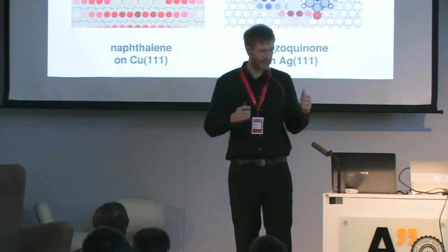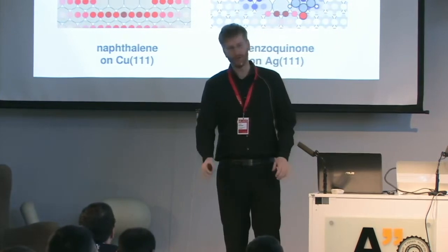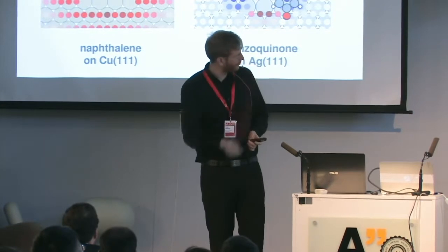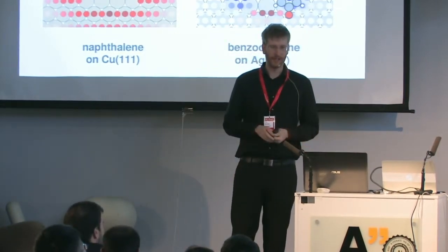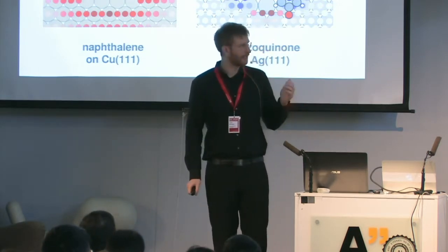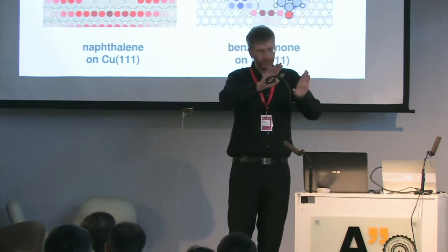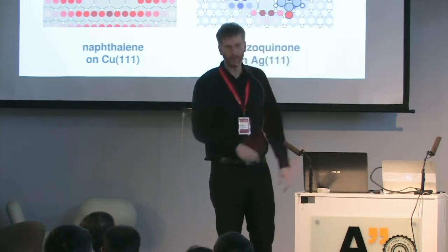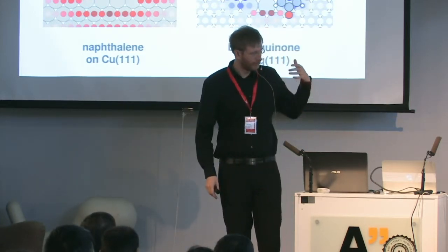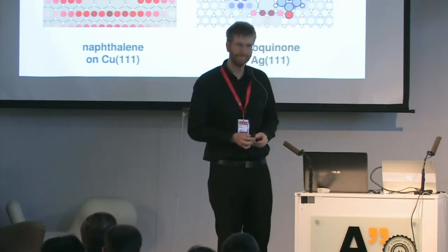So we assume that the molecules, if we put them in a densely packed layer, remain in the same or relatively the same position. We have tried this out for the system of naphthalene. We did some calculations where we optimized the geometry by doing gradient descent, and there we didn't see significant changes in the geometry, except if we put the molecules far too close together, but then the energies were so high that they wouldn't show up in experiment anyway, and we wouldn't predict these as low energy configurations anyway. Okay, we have time for a last question.